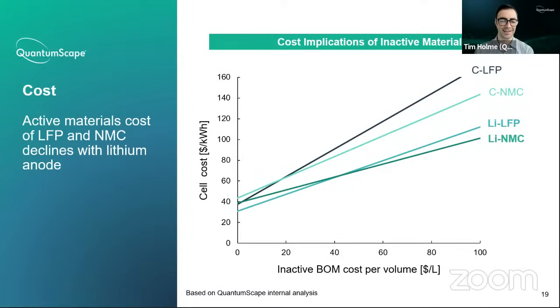So this is a pretty interesting and on one level simple chart, although it illustrates something pretty interesting. If you assume that there's no inactive cost of the cell, then you're basically at the cell cost of raw materials, active materials only. And then you can draw lines out here that are lines of constant energy density of the cell, basically. Energy density per inactive material of the cell. And what you can see is a crossover between where LFP and NMC become the lower cost cell. So if you start off talking about a carbon NMC type EV cell, and you have expensive inactive materials, it is the lower cost material because you have higher energy density in the NMC itself.